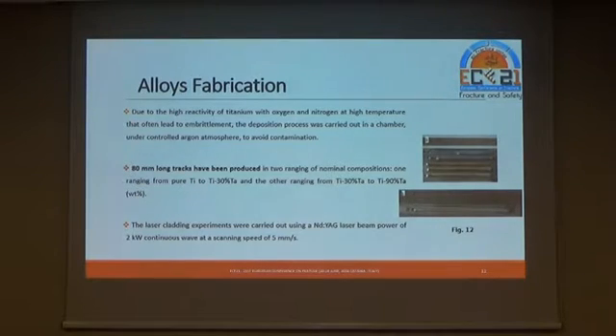Due to the high reactivity of titanium with oxygen and nitrogen at high temperature, that often leads to embrittlement, the deposition process was carried out in the chamber under a controlled argon atmosphere to avoid contamination. 80 mm long tracks have been produced in two ranges of nominal composition. One ranging from pure titanium to titanium 30% tantalum, and the other ranging from titanium 30% tantalum to titanium 90% tantalum. The laser cladding experiments were carried out using an Nd:YAG laser beam power of 2 kilowatts, continuous wave, at a scanning speed of 5 millimeters per second.